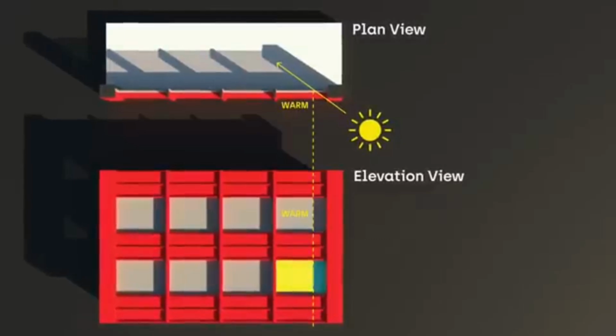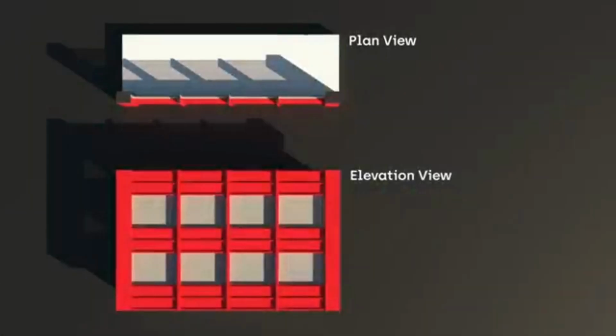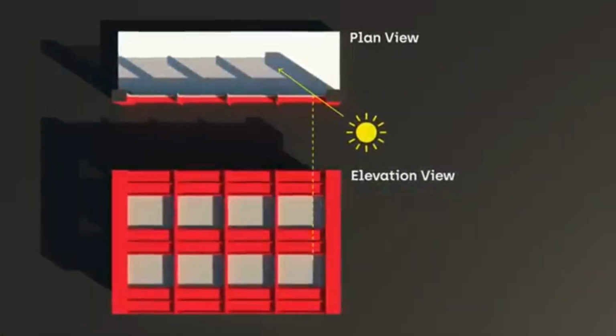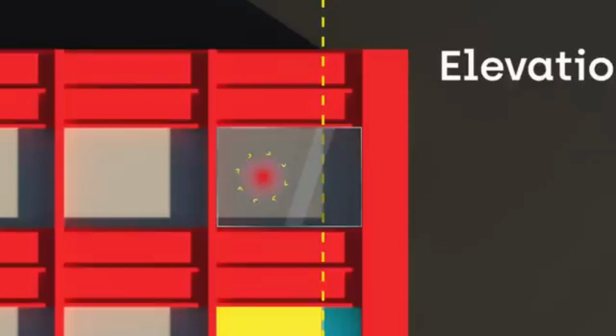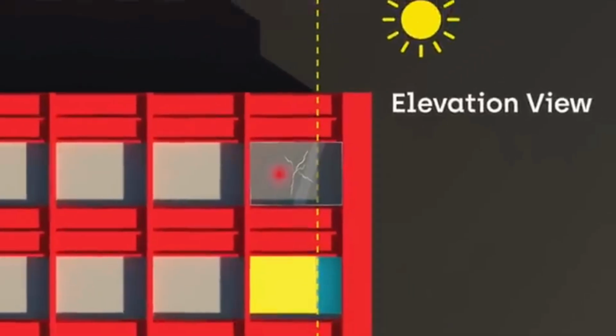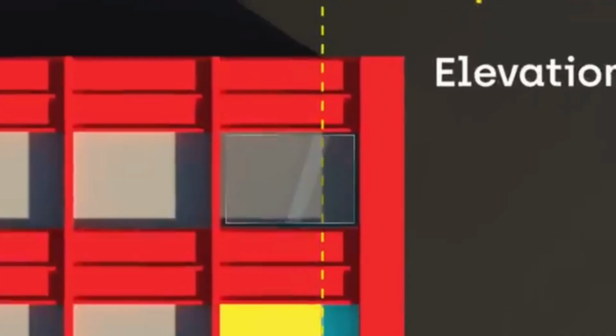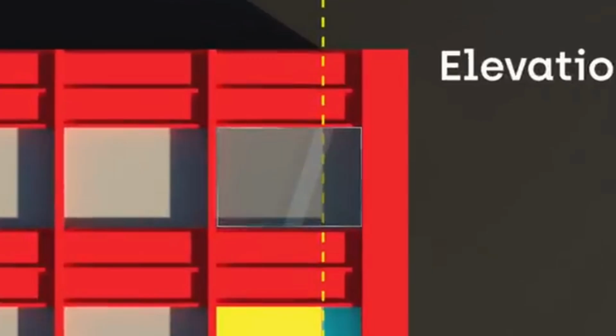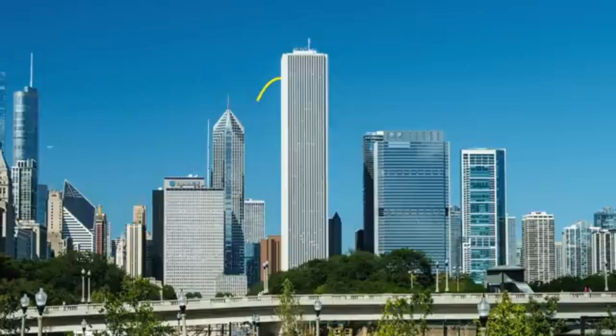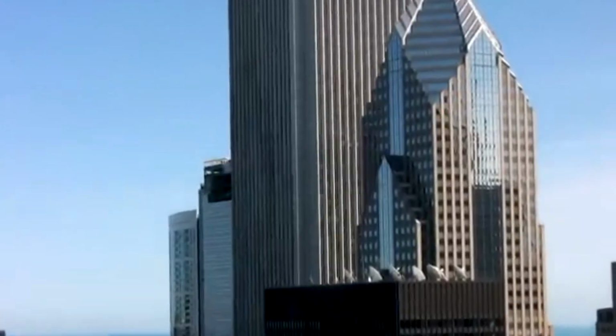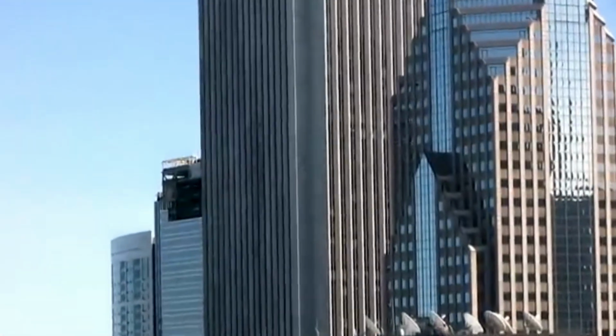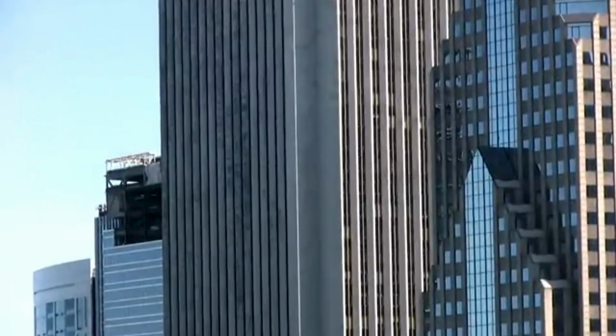Then there's thermal stress, a silent killer that designers must anticipate. When sunlight strikes a glass panel, the center heats up and expands while the edges, shaded by the frame, remain cooler. This temperature difference creates tensile stress at the edges. If that stress exceeds the glass's edge strength, breakage occurs. This is particularly dangerous with insulating glass units that have solar control coatings. The coatings manage solar heat gain but can exacerbate temperature differentials. The solution lies in proper thermal stress analysis during design, especially for large panels with high-performance coatings.